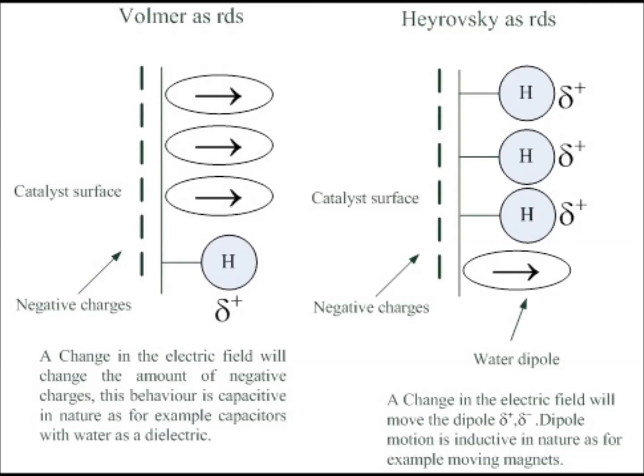When Volmer is the rate determining step, the system behaves capacitively, and for Heyrovsky, the system becomes inductive.